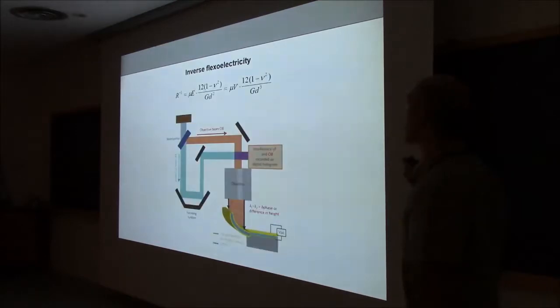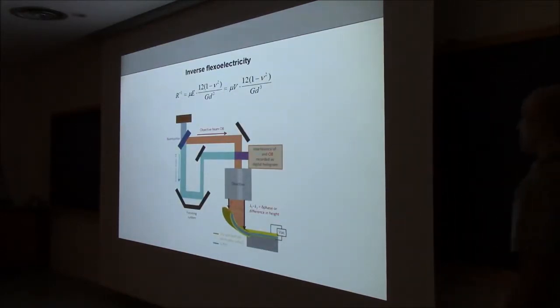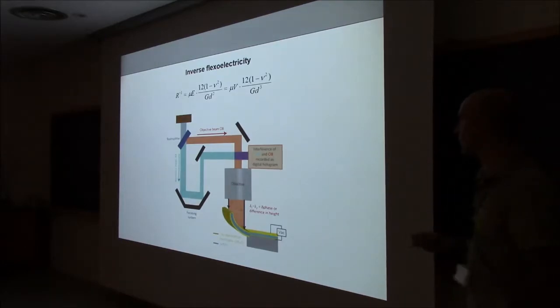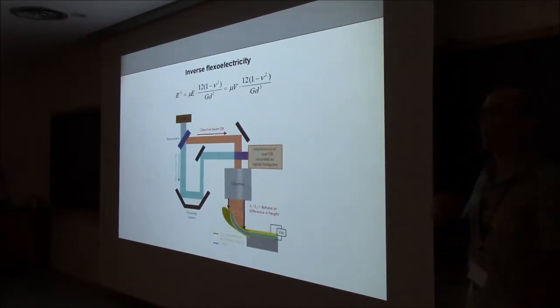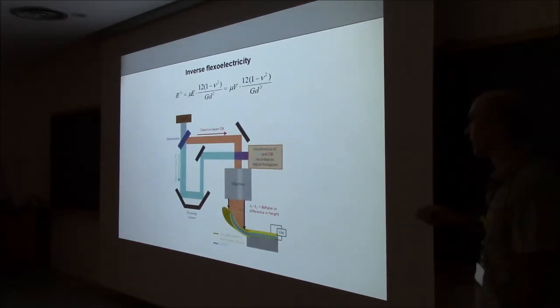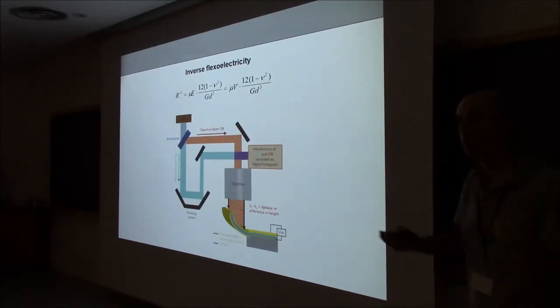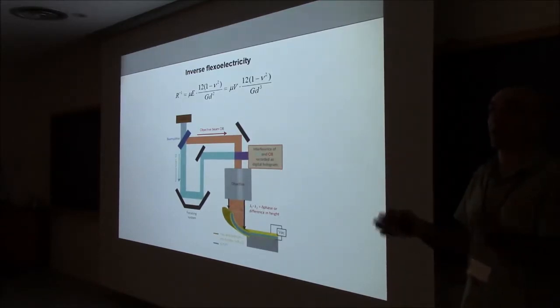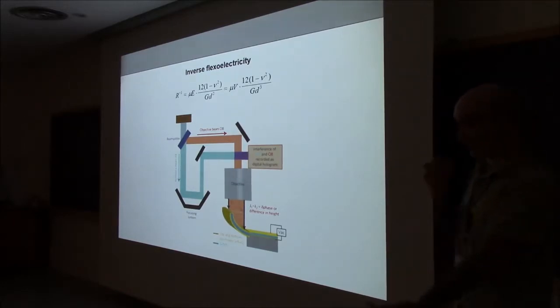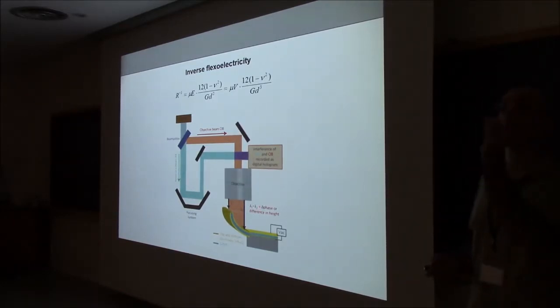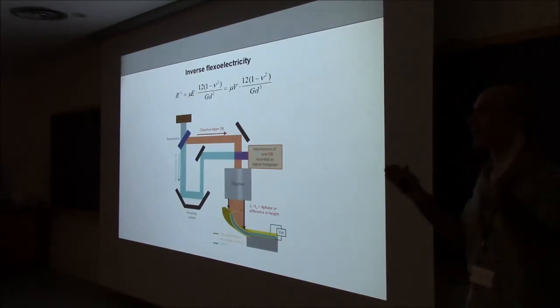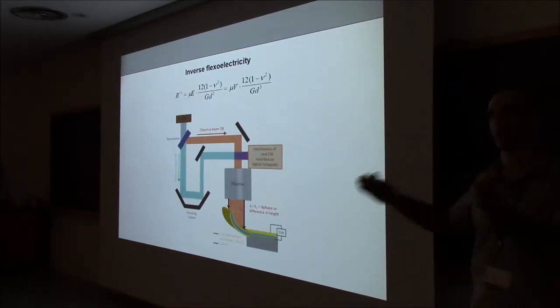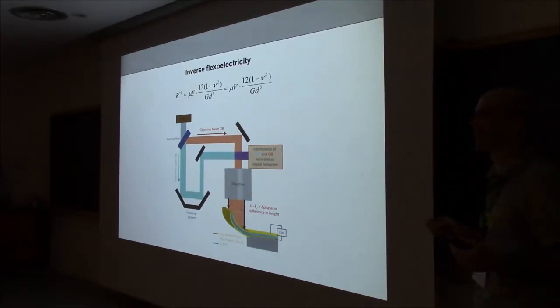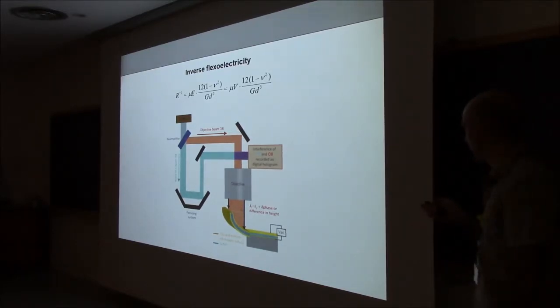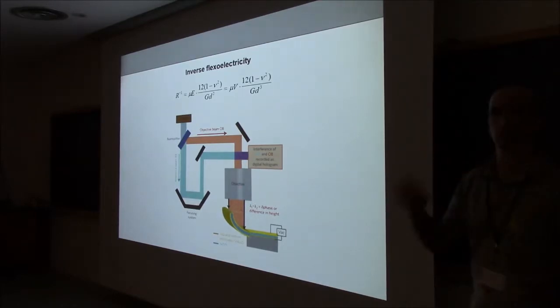Yes, that's direct flexoelectricity. Inverse flexoelectricity is you apply a voltage and something bends. So we take our parallel plate capacitor, we apply a voltage, and we measure the deformation by whichever means you have. In our case, we have an interferometric microscope, or a holographic microscope. Instead of taking photos, it takes holograms. It is in 3D, and the vertical resolution is interferometric, which means it's much better than the wavelength. Whereas the lateral resolution is half a micron, the vertical resolution can be nanometric. You can also do this kind of experiment by Doppler vibrometry, for example.